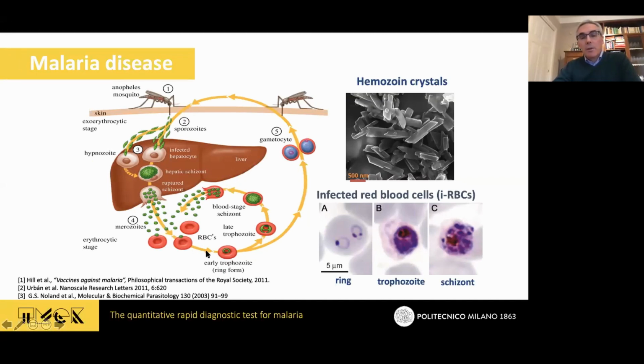They attack the red blood cells, and inside the red blood cells they feed on hemoglobin and transform it into this strange and very interesting hemozoin crystal that you can see here. These are crystals with a brick-like shape. The typical dimension is on the order of 500 to 700 nanometers in length, and the section is on the order of 100 to 200 nanometers. And interestingly enough, as we will see, these crystals are magnetic.